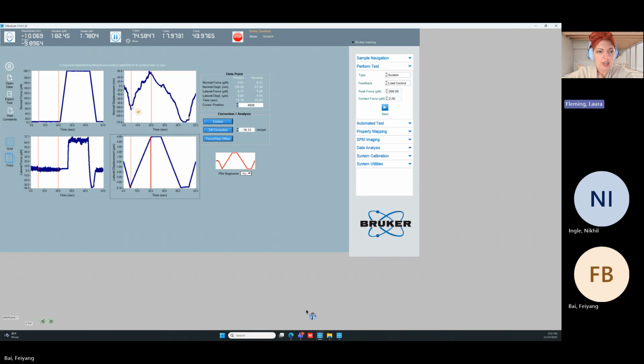So I'm going to take these 2 points. Those 2 points, it's more accurate. Then I hit tilt correction, and it takes whatever is in between these 2 bars in the normal displacement and says that should be 0. That is the tilt. Then it applies it to all of the data in the normal displacement to correct for it. So I hit tilt correction, and it made this 0 to 0. Now we get a more accurate normal displacement.